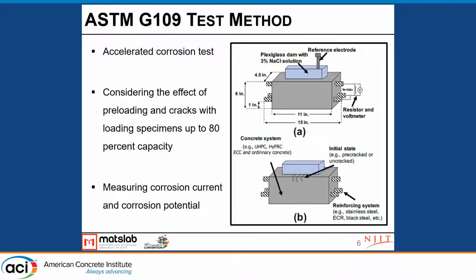So we are going to test these three materials for corrosion using the ASTM G109 test method. This is an accelerated corrosion test. We are going to make concrete beams with two layers of rebar. The rebar at the bottom is the cathode, and the rebar at the top is the anode. We are going to pond these specimens at the top with a salt solution, so the salt penetrates into the concrete and initiates corrosion at the top rebar.